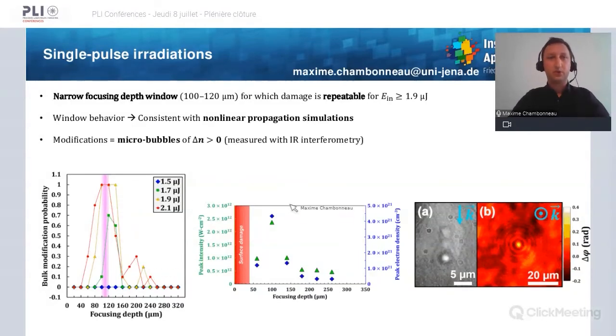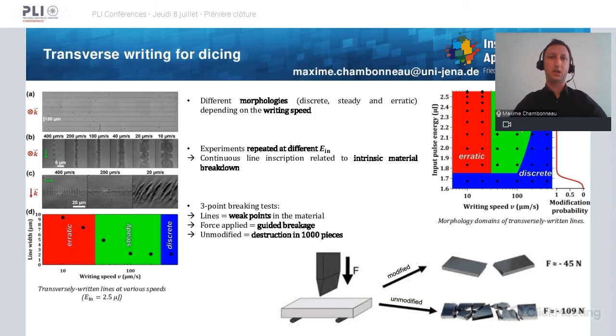And this window behavior was consistent with nonlinear propagation simulations, as shown here in the middle, where you can see that the peak intensity as well as the peak electron density is higher when the focusing depth is around 100 micrometers. Concerning the modifications, well, they consist of micro bubbles aligned along the optical axis with a positive refractive index change as measured by infrared interferometry.